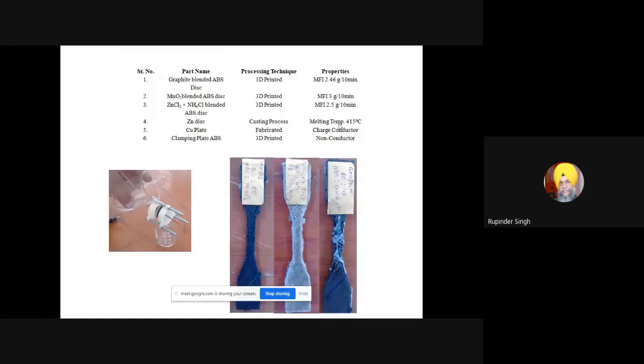So what we did is we assembled, but we were not able to get the output. So you can see here is the assembly. So here are some copper wires. Now to get some output, what we did is we dropped some quantity of the acetone at the interface, so that if there is a hindrance by the outer layer of the polymer, it gets dissolved, and finally there should be a chemical reaction. So we were able to get the desired output.